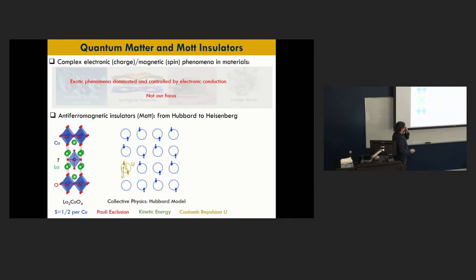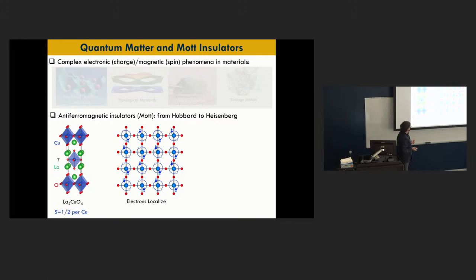As a result of this, there is a localization of the electrons on the lattice sites. But because of the Pauli exclusion principle, two neighboring sites have opposite spin. So that's the emergence of what we call an antiferromagnetic insulator out of a system with one electron per unit cell that should otherwise be a conductor. And so then I can bring back my crystal, repopulate it, and put some spins, and I have an antiferromagnet. So lanthanum copper oxide, because of strong correlations between electrons, is an antiferromagnetic insulator.